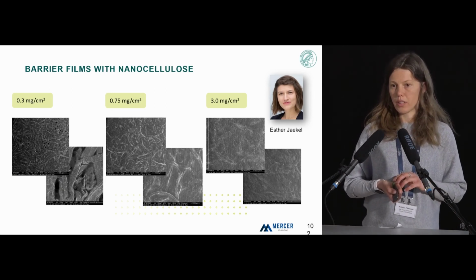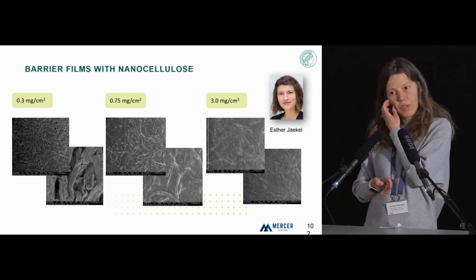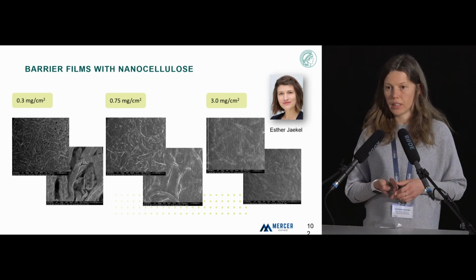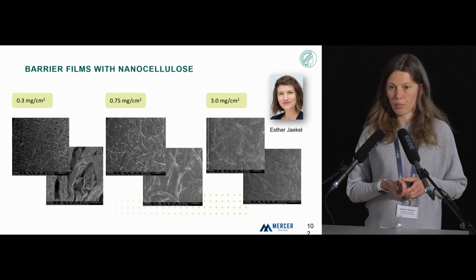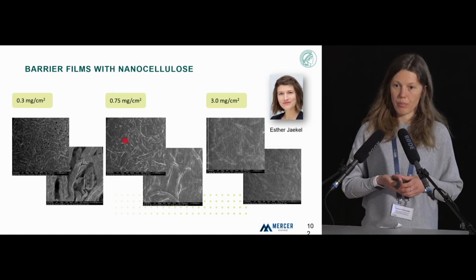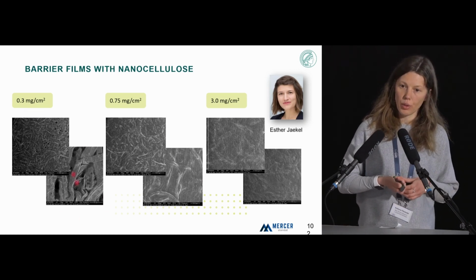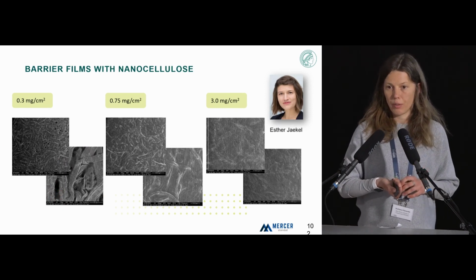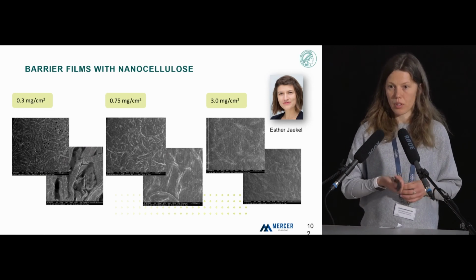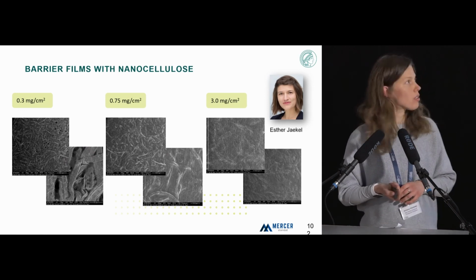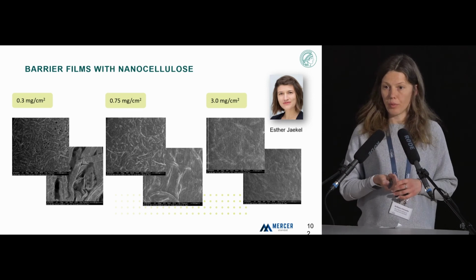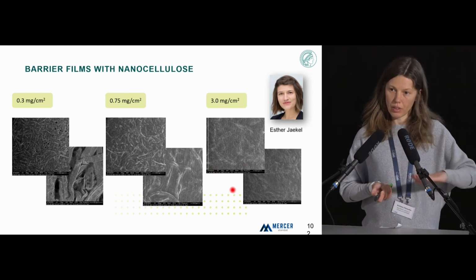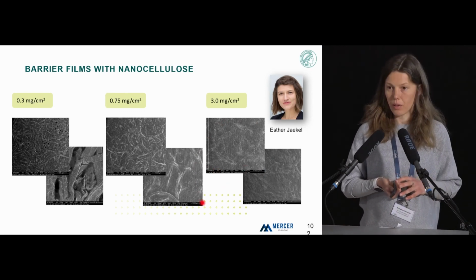So our idea there behind was to have better contact with the cellulose, which is usually negatively charged, of our nanocellulose particles. So you can see with less loading of the CNC, it's kind of like wraps around all the fibers. I would suggest the positive charge of the nanoparticles plays its role there. We found the optimal load of CNC to cover the surface completely.